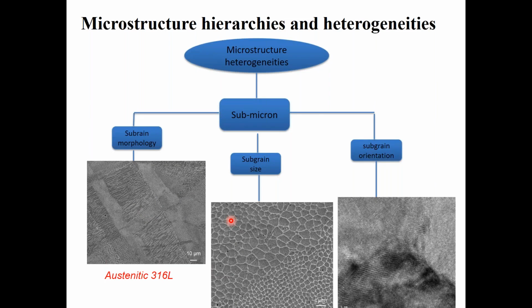So here I will say that it is a hierarchical structure. If we look closely, we have bigger grains and we have subgrains inside. The subgrains can also be of different sizes, as you can see in adjacent grains. And within these subgrains, if we look at the grain boundaries, we can find the segregation of certain elements and also some oxides. So it's a hierarchical and heterogeneous microstructure, which opens up the possibilities to achieve properties that we cannot get in conventionally cast or produced steels.